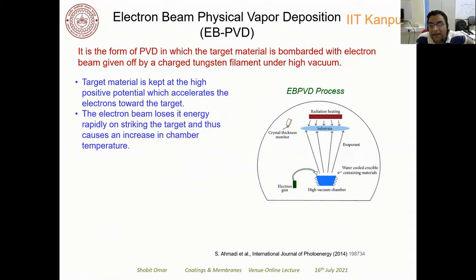Here you are using an electron gun to locally heat the target. Of course it is placed inside the chamber where the vacuum is there, but the vacuum is not as high as what you have in the thermal deposition techniques. Also, you can see that the target material is kept at high positive potential, which accelerates the electrons towards the target, and this electron beam loses its energy, and this energy is absorbed by the target material,